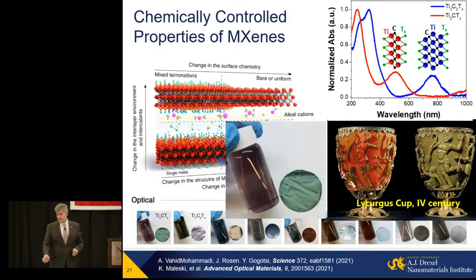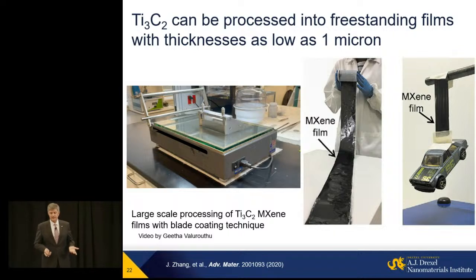So you see, if you move to titanium 3C2, just add one layer of carbon element and one layer of titanium. The absorption peak will shift to 780 nanometers. So it will now become green in transmission, and kind of a violet reddish in reflection here. So this is just one example.